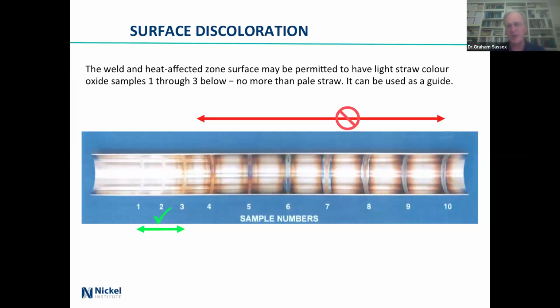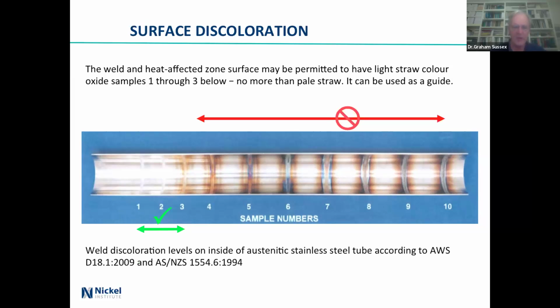The European hygienic designers, food people, have about the same, except they have a lot finer gradation of changes in oxygen level. The weld discoloration on the inside, according to AWS D18.1, 2009, and yay, Australian AS/NZS 1554 part 6, 1994. But that basically came from Sandvik, so perhaps it's just Sandvik. And similar results for Duplex. So there you are. That's the level of oxygen you can afford to have.